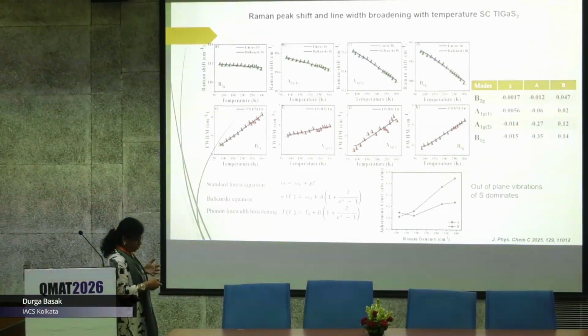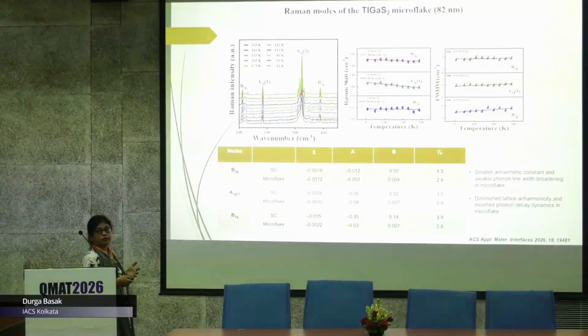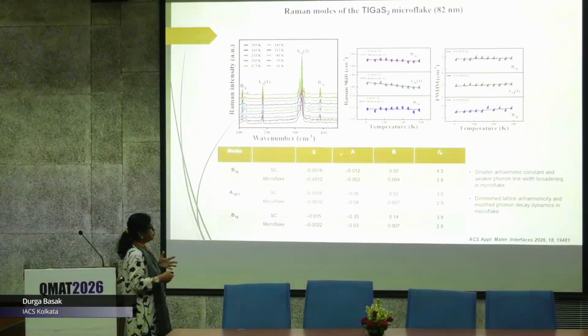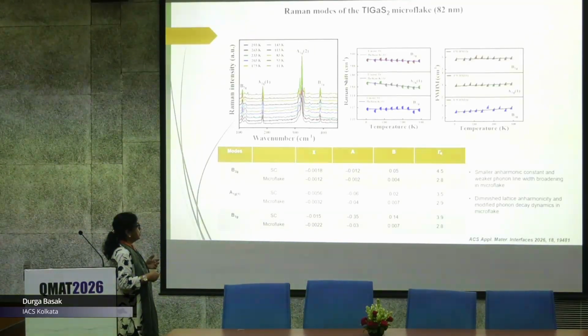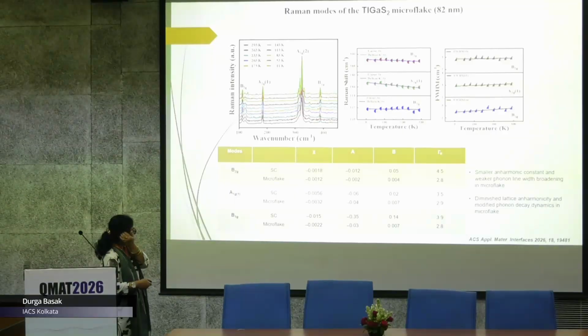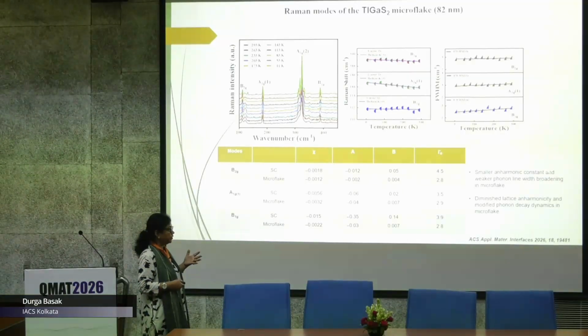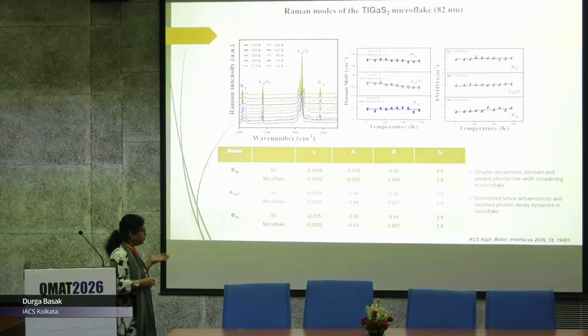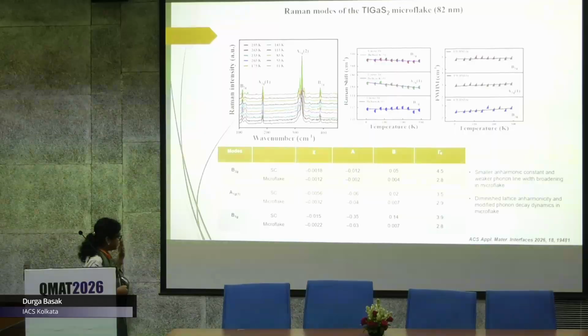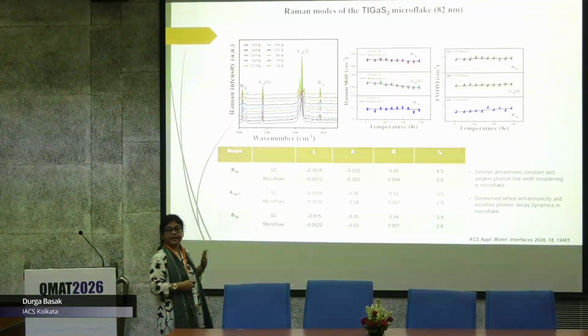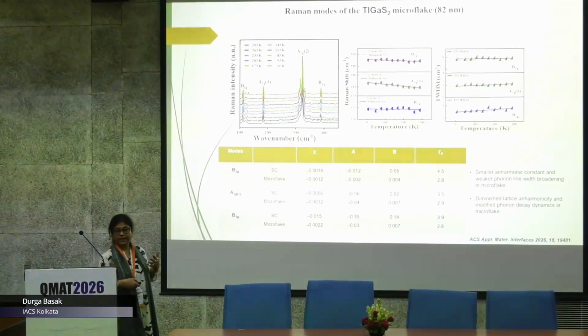And you must note that the constants are these, and when we go to the microflake of 82 nanometer after exfoliation, we see the values become much less. Here I have given this table where I have compared the values of chi, A, B with those of the single crystal. You see all the anharmonic constants are lesser in the case of microflakes. So from this result we can say that smaller anharmonic constants and weaker phonon line width broadening happen in microflakes. This diminished lattice anharmonicity tells us that the phonon decay is different when we go to microflake.